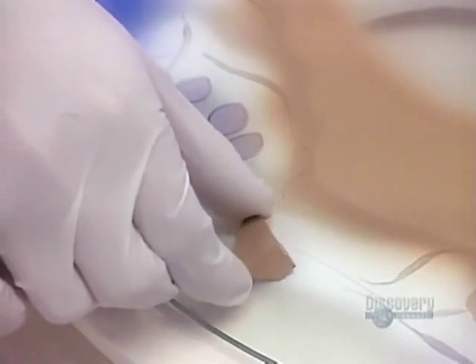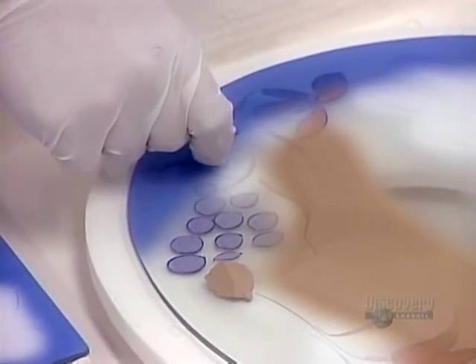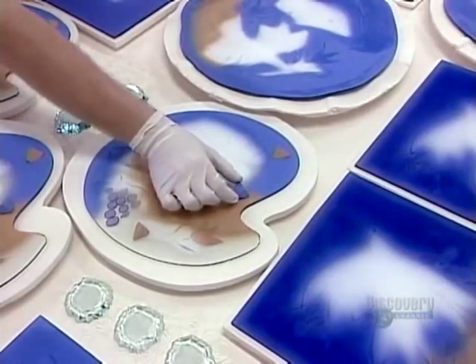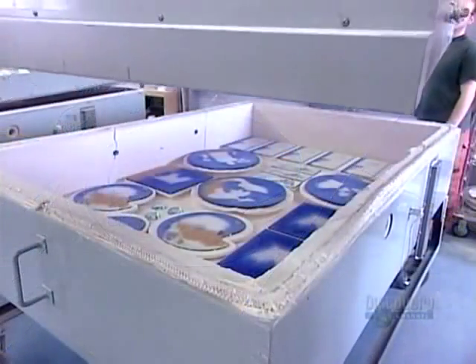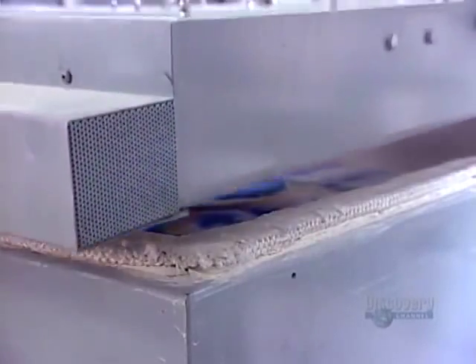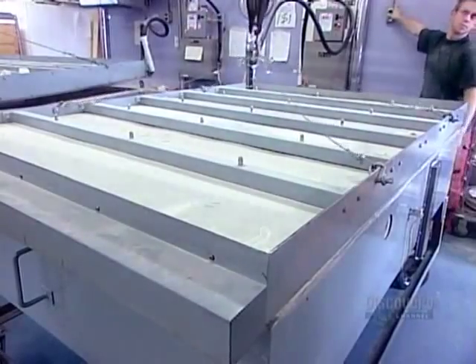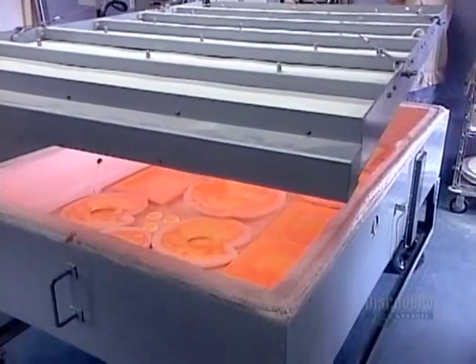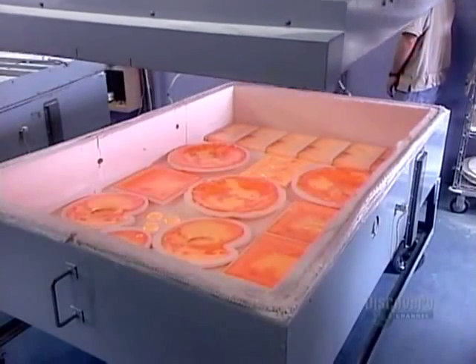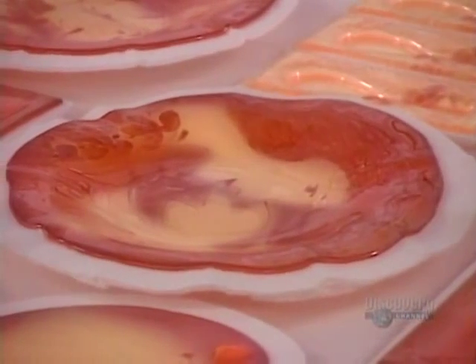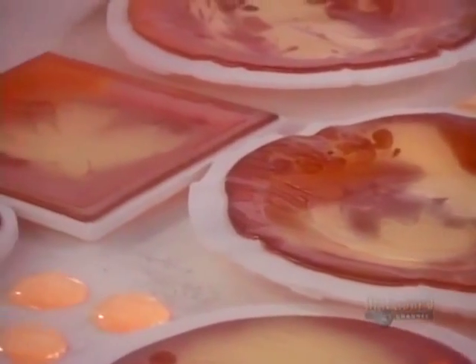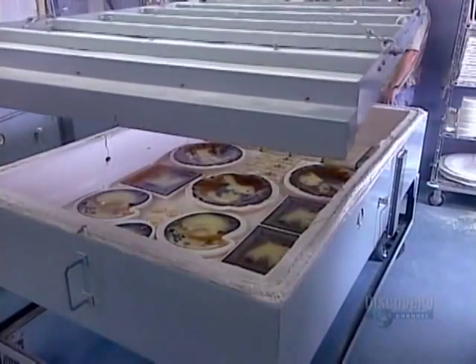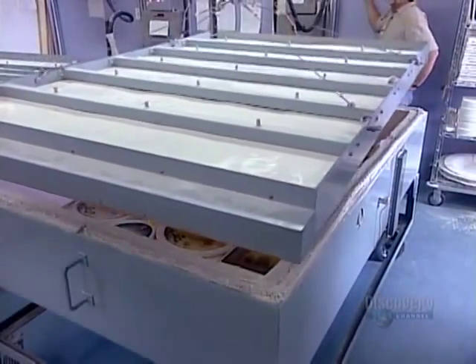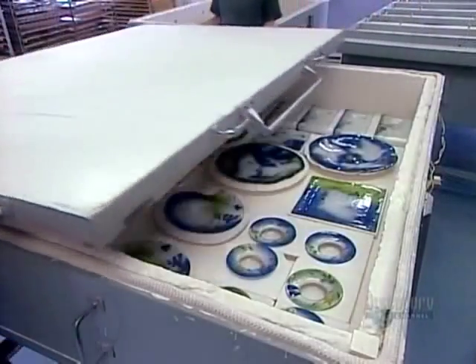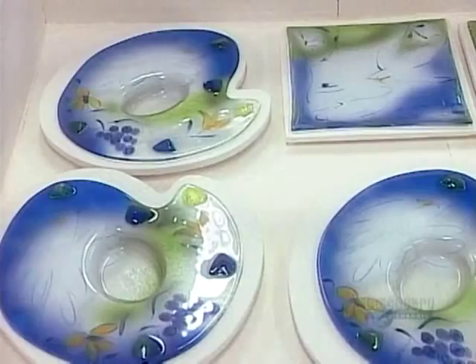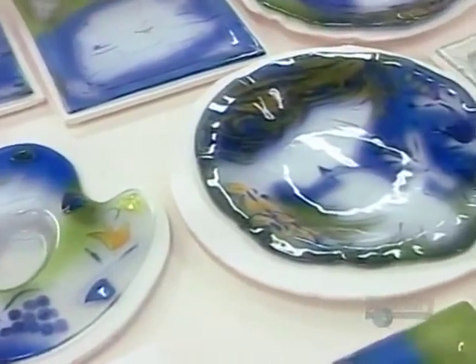These small pieces of glass will become the paint pots on this glass replica of an artist's palette. It takes an hour and a half for the kiln temperature to climb to a scorching 843 degrees Celsius. At peak temperature, they open up briefly to make sure that everything is progressing well. The glass at this phase should be the consistency of maple taffy and glowing bright red. If it is, they can close the kiln and begin the cooling phase. 6 hours later, the glass pieces have hardened into the shape and texture of their respective molds.